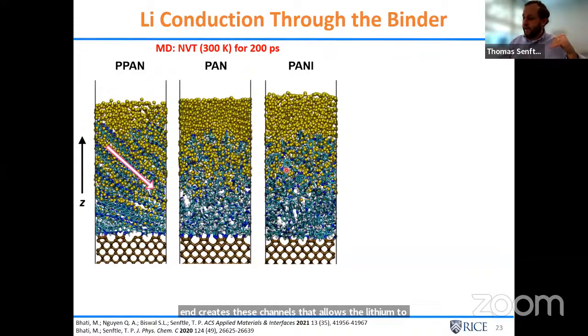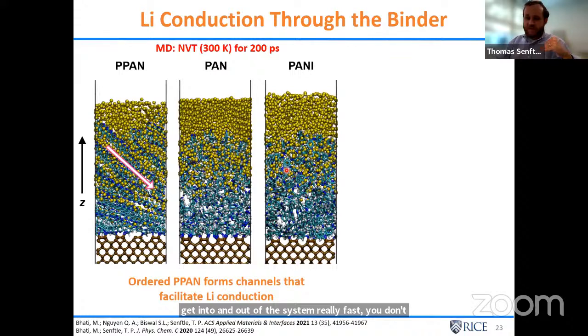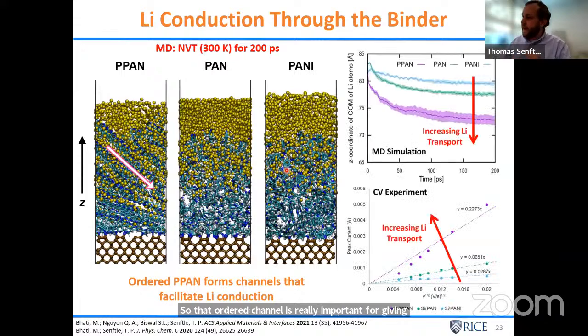You don't get that with the pan and the polyaniline. So that ordered channel is really important for giving you the rapid ion conduction. And if we compare that, this is just a picture of where the lithium is as a function of the simulation time. It gets closer to the surface faster for the p-pan. Experimentally, if we look at the measured lithium conduction rates, they're fastest for the p-pan. So again, there's some connection to the experimental observables.